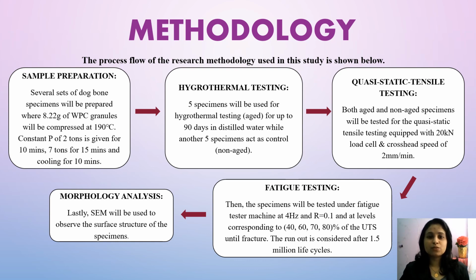5 specimens will be used for hydrothermal testing, referred to as aged, for up to 90 days in distilled water, while another 5 specimens act as control and are referred to as non-aged. Next, quasi-static tensile testing. Both aged and non-aged specimens will be tested with a 20 kN load cell and crosshead speed of 2 mm per minute.